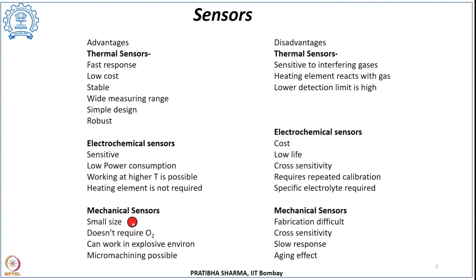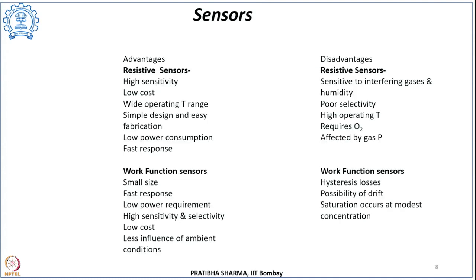For the mechanical sensors that we studied, their size is small, they do not require oxygen, they can even work in the explosive environment, and micro machining is possible for them, but that makes it difficult to fabricate. That is the disadvantage of mechanical sensors. Then there could be cross sensitivity, slow response, and aging effect is seen in mechanical sensors. In the resistive sensors that we have seen in the previous class, they have a high sensitivity, low cost, wide operating temperature range, simple design, and they are easy to fabricate. They require less power consumption, they have a faster response, but the disadvantage is they can have sensitivity towards other gases and humidity. So there is a poor selectivity towards hydrogen, they can have higher operating temperature, require oxygen, and they are affected by the gas pressure.